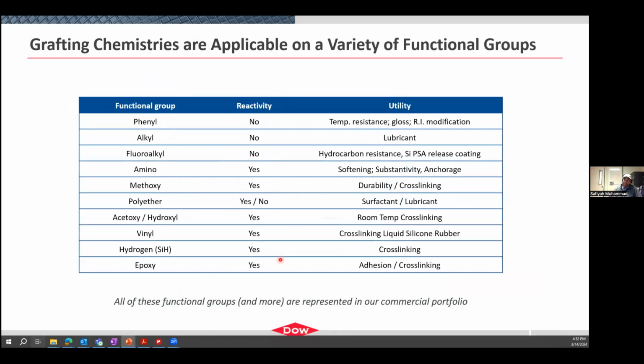And so you can change them out for different groups and achieve different properties based on the different groups that you have. Whenever you want to make silicone more compatible with an organic surface, we will often exchange it out for something like a propyl group or an alkyl group, right? If you want to make it a bit more temperature resistant, you'll change a methyl group out for a phenyl group, and we do that all the time. This is a list of some of the groups that we use within Dow and some of the groups that are represented in our commercial portfolio.